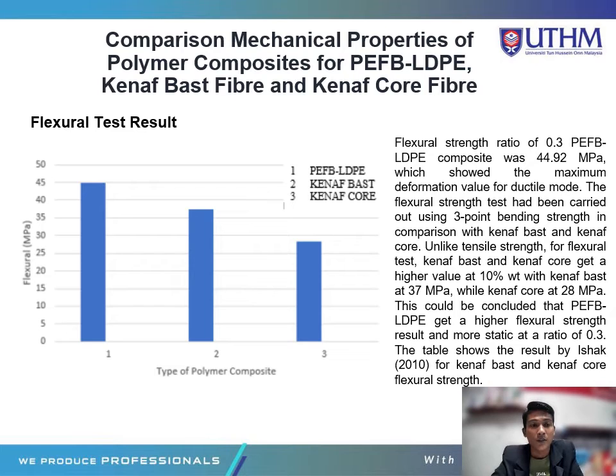For the flexural test result comparison of PEFB LDPE with Kenaf bast fiber and Kenaf core fiber, the flexural strength ratio of 0.3 PEFB LDPE composite was 44.92 MPa, which showed the maximum deformation value for ductile mode. The flexural strength test had been carried out using 3-point bending in comparison with Kenaf bast and Kenaf core.